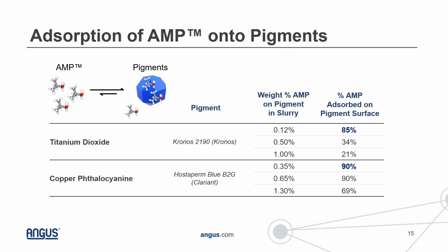And so if you're going to have a good dispersant, really the first key property you need is a very strong interaction with those pigment surfaces. AMP as a material has that property, and we demonstrate that here. This is looking at either titanium dioxide or at a colored pigment.